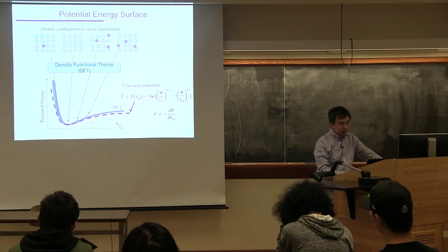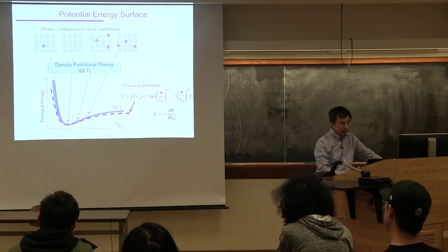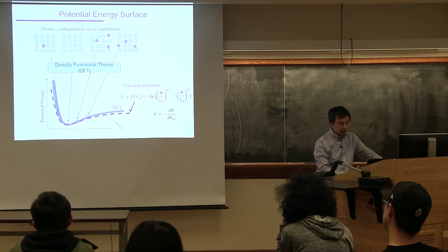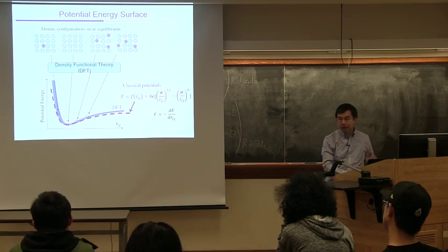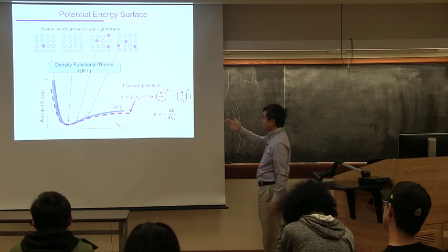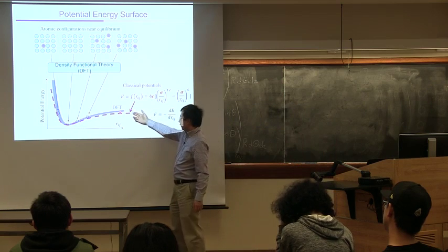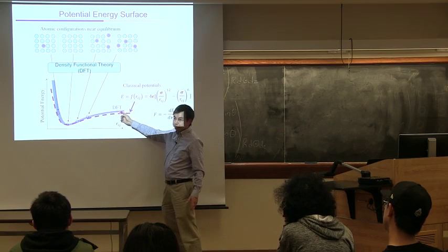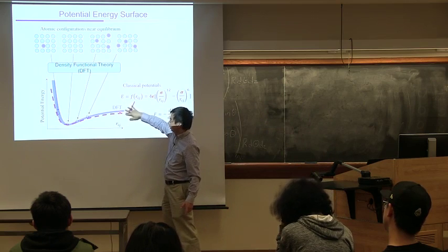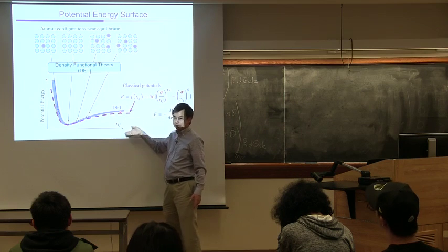Again, for thermal purposes, we care more about the equilibrium as well as somewhere away from equilibrium, but not too far, right? So we want to make sure that the fitting near equilibrium is the best. It may turn out that when you go far away from the equilibrium, the errors become larger, which may not be so important for thermal, but this fitting may not be so good for chemical reactions, where you really care about the energy near the breaking point, right?